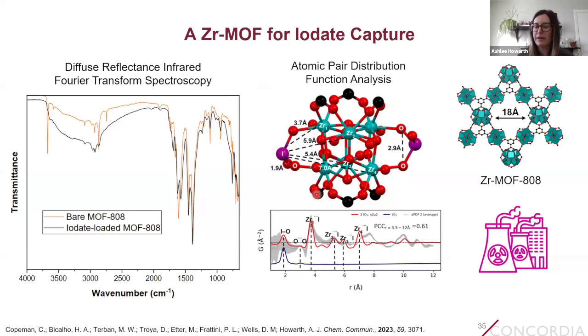We can also use atomic pair distribution function analysis. So this is data that's collected using total X-ray scattering analysis from a synchrotron, where we can get information about specific atom to atom or atom pair distances in our material. And so we can compare the experimental data to a bunch of computational simulations where we simulate all the different ways we can envision iodate interacting with our MOF node. And what we see is that this is the model that fits with the experimental data the best. So showing that our iodate oxyanions are interacting with our node in this bridging fashion.